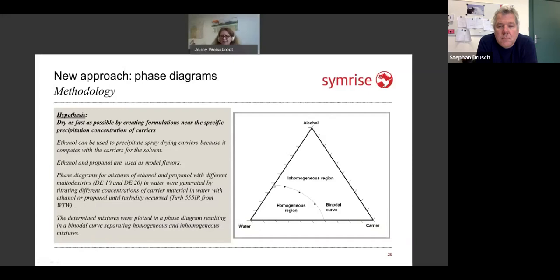I said, okay, what happens during drying? You always reach a point where your carrier material is no longer soluble within your solvents. What happens at this point, we are not quite sure, but it's possible that it precipitates spontaneously and includes your active. To find out if this really happens, we established ternary phase diagrams, which represent mixtures of water, carrier, and an alcohol. With titration curves, we created different mixtures of water and carrier, and then made a titration with ethanol. Just by measuring the turbidity, we found the point where our carrier starts to precipitate.